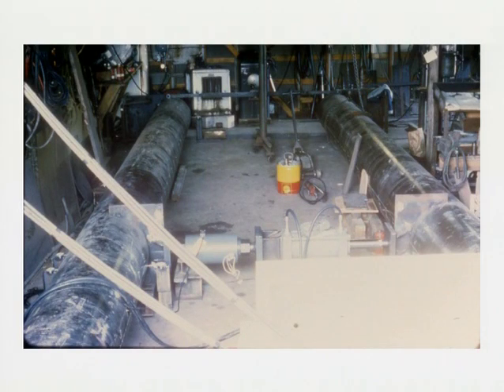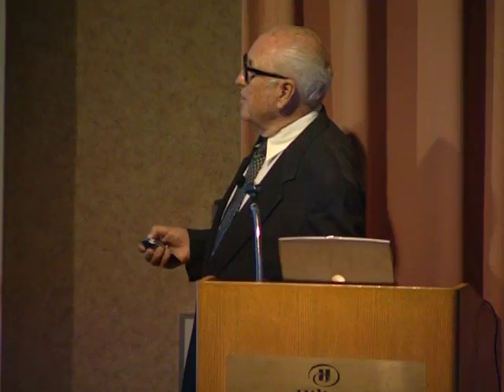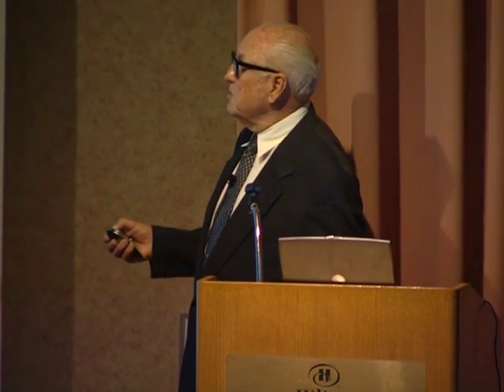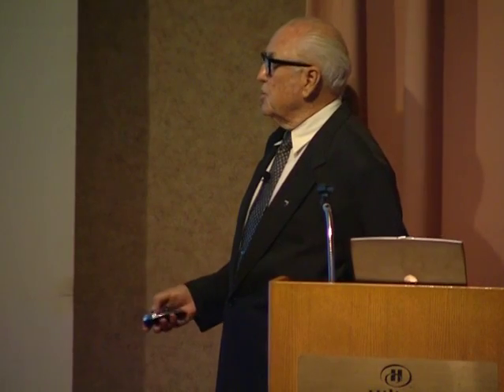Here's a very important consideration. It's not especially a good slide, but what we have is a calibration test in progress. Right here we see a hydraulic ram and a load cell, and we're putting applied loads through a particular point, through this plate right here, which gives us an exact position. Then we measure the results in terms of the strain gauge reading up and down the length of the pile. Knowing the bending moment, we have a calibration curve for strain gauge reading as a function of bending moment for every position along the length of both piles. Those calibration curves could be developed analytically, but we get a more precise result using the calibration shown here.